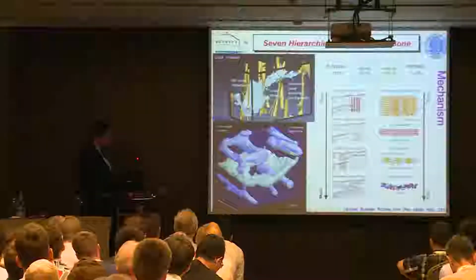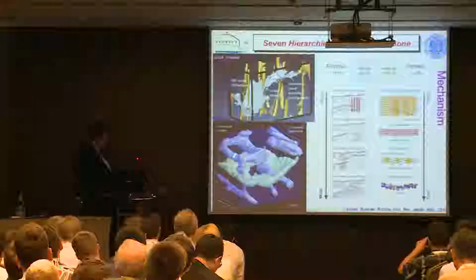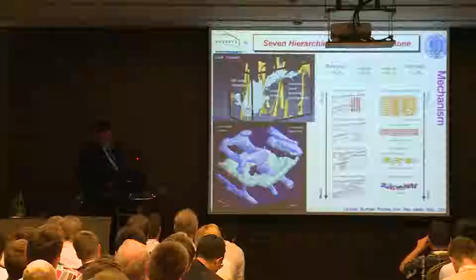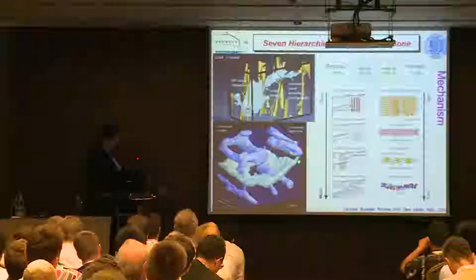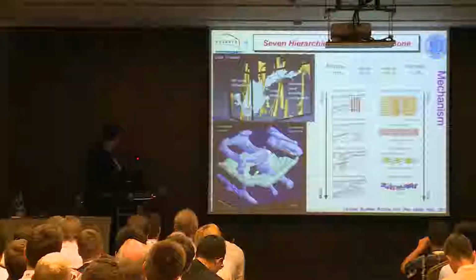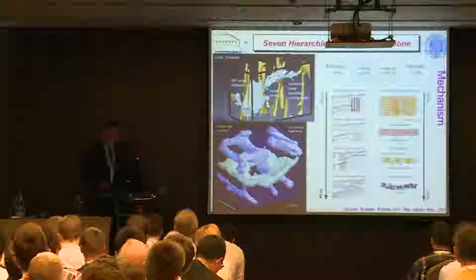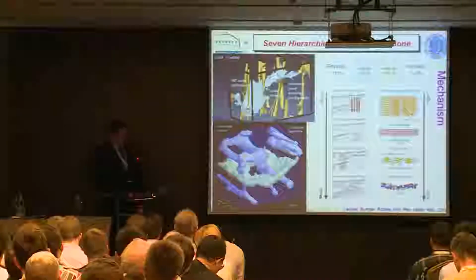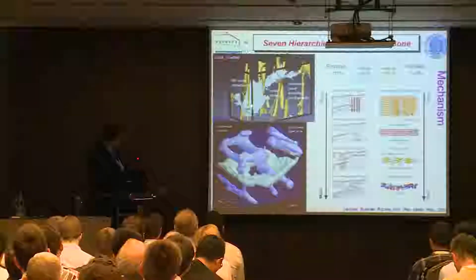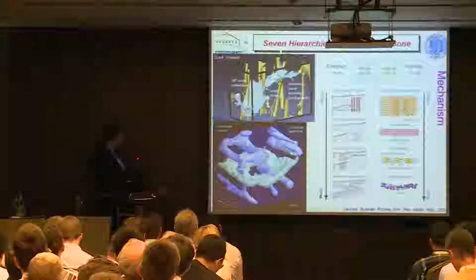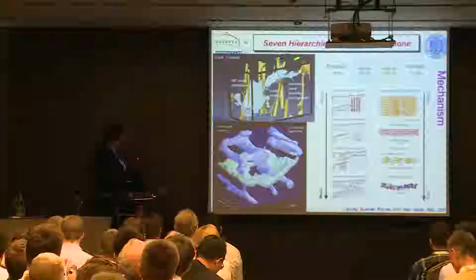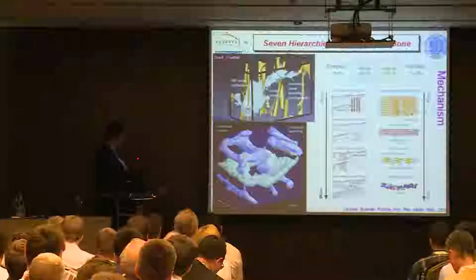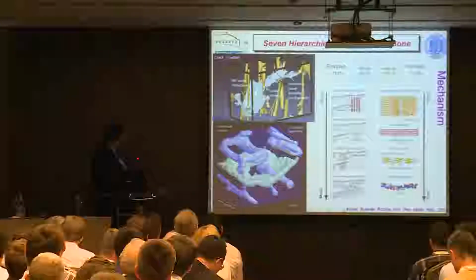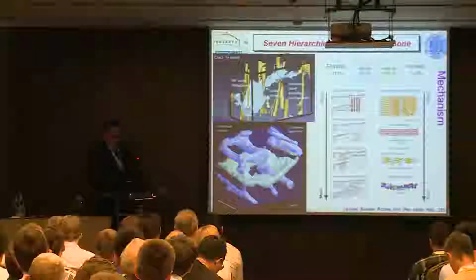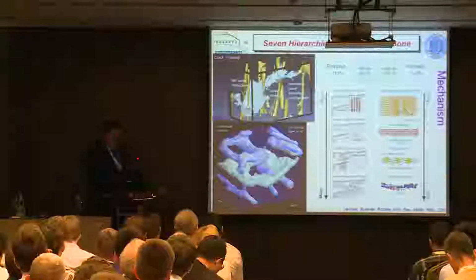So if we look at a typical example, this is tomography. I can show some examples of these mechanisms. This is a three-dimensional tomography of bone. This light blue is, of course, the Haversian canals. This white area is the crack. This is the front of the crack here. And these dark blue areas behind the crack tip are these regions of uncracked ligament bridges. And then the deflection is very well shown here. These are the osteons, these yellow columns. This piece of bone is being pulled vertically, so the crack should propagate, behave itself, perpendicular to the maximum tensile stress. But you can see in the white area that the crack deflects dramatically as it encounters these osteons. And the deflection actually is more than in plane.